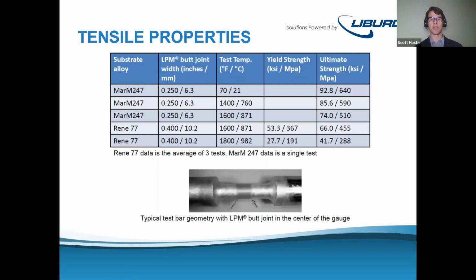Let me just touch on the tensile properties before we show you some more about that repair. Not everybody has all of the mechanical properties memorized for all these components. Generally, the ultimate tensile strength and the yield strength are going to be higher than the typical weld alloys that are used in a lot of repair shops because they're easy to weld and can build up material easily. But the key thing to show here is that we're not just doing small little repairs. We're testing these at 250 thousandths of an inch or 400 thousandths of an inch wide. So you can see in here, this is a cyclic test bar that we've put together, and you can see the 1/4 inch LPM deposit here in the middle, and that will run out to understand the fatigue resistance of the component.